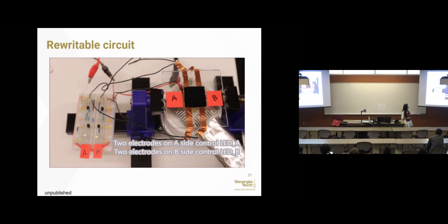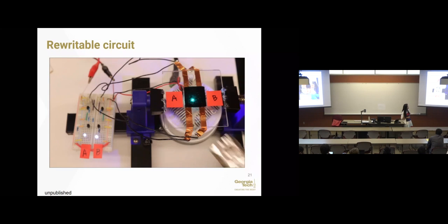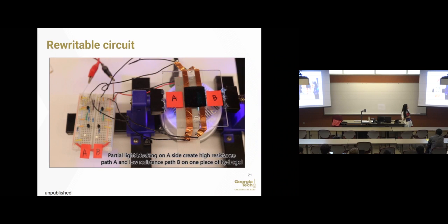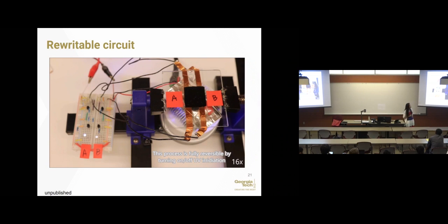Just to play around with this, this is a simple demonstration my student did. This is a piece of gel, and it's connected to two LEDs through these two strips. So it's two circuits, and when we shine light, both dim, right? And when he covers one side, only this side is conductive, and this side is not. So you can see we can control the circuits independently. We call it a rewritable circuit. So you can use light to induce a local conductivity change of the material.